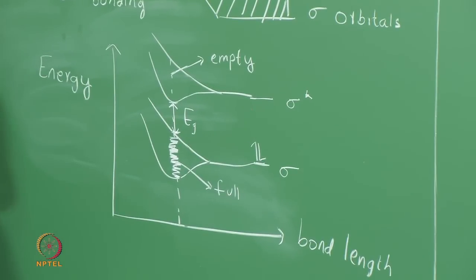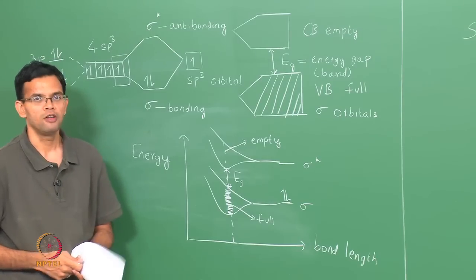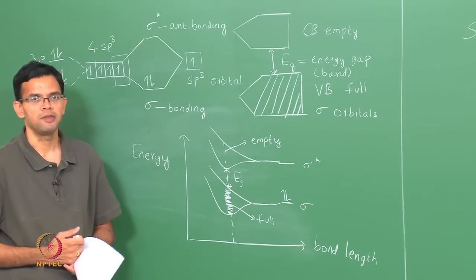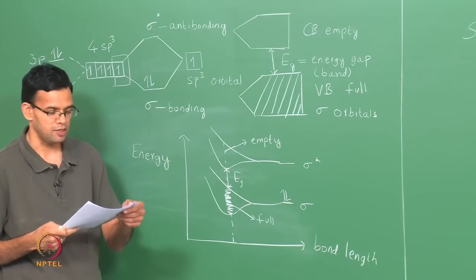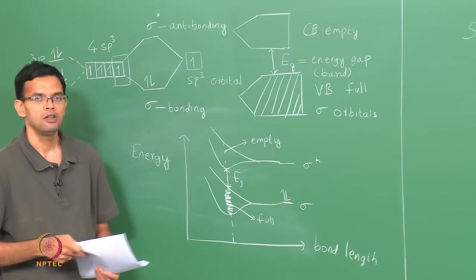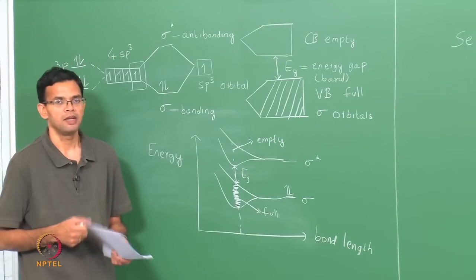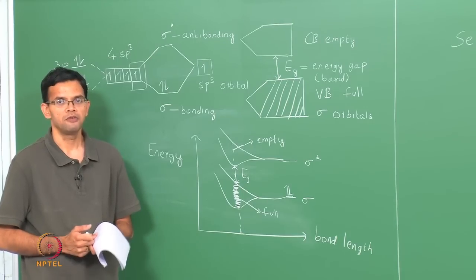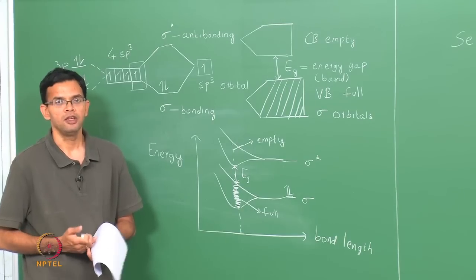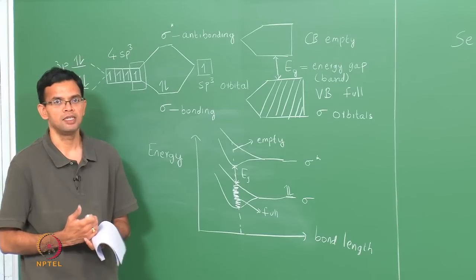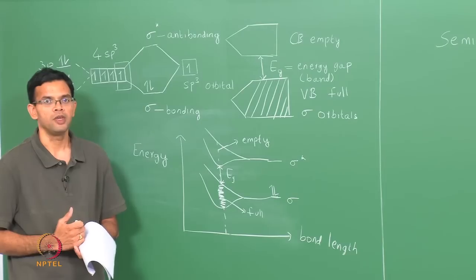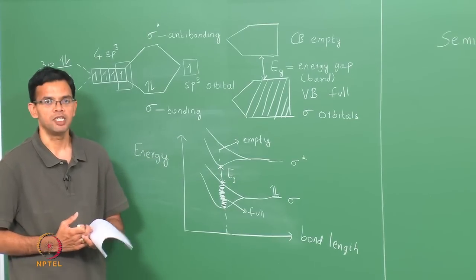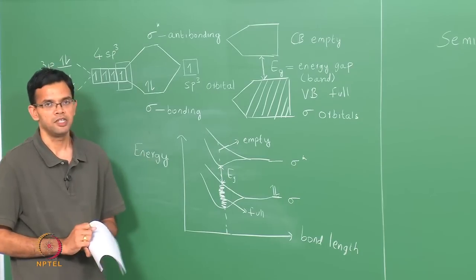This model for silicon can be applied to germanium, which lies in the same group and similarly has S and P orbitals hybridizing to form SP3 orbitals. We can extend this model to insulators as well. For example, in sodium chloride, bonds are formed by Na+ and Cl− ions, so it is the ions forming the bonds and the bands — the same picture, but the details change depending upon the material.